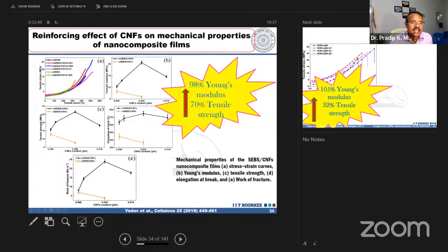Then you will see here, 0.005 phr of the cellulose nanofiber is giving huge mechanical improvement. It's a very huge mechanical improvement. Whatever the base material was, somewhere around 15, we are getting somewhere around 27. We are getting a 98% increase in Young's modulus and 70% in tensile strength. And if you see the tensile strength, whenever you use unmodified cellulose with unmodified SEBS, it is decreasing the tensile strength.